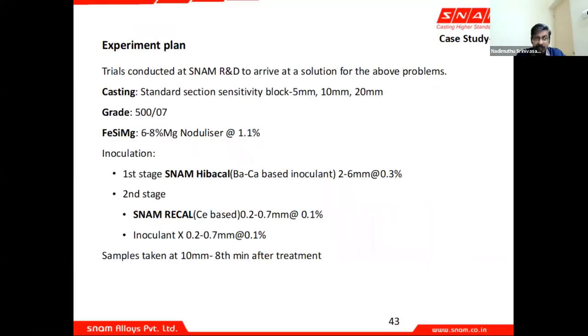So we had a trial conducted here, and we took a sensitivity block of 5, 10, and 20 for a grade of 500 bar 7, with 6 to 8% magnesium. This is the least among the grades that we are supplying in India, at 1.1% addition rate. For the first stage, we used barium calcium based Hibacal at 2 to 6. For the second stage, you need a control also. So we used one with cerium based Recal at 0.2 to 0.7%, and another is inoculant X, which is just a pure ferrosilicon based inoculant of the same size and same addition rate. And we took samples at the 10 mm at the 8th minute for analysis.